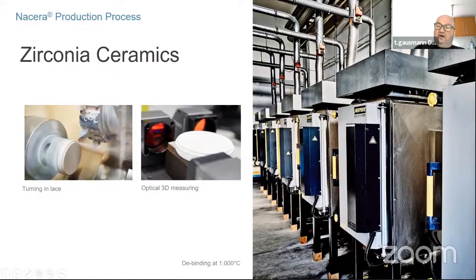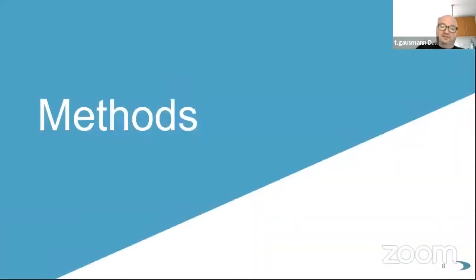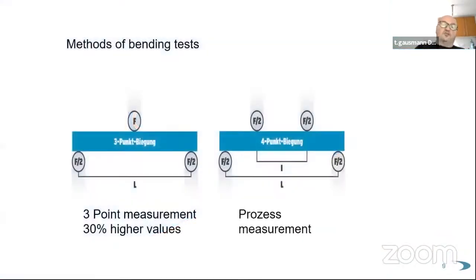on the bottom, the discs are colder. On top of the furnace, they are a little bit hotter. And the ones that are hotter have a different shrinkage. So with us, it's not an average shrinkage factor, it's a shrinkage factor for each and every disc, making it very, very precise.